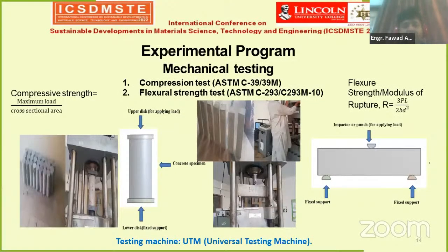Now, please focus on this slide. This is basically the conclusion of my experimental program. Two types of tests were performed: compression test and flexure test. Compression tests were performed by standard ASTM C39, and flexure test was performed as per ASTM C293. The compressive strength was found by the formula maximum load divided by the cross-sectional area of the cylinder.